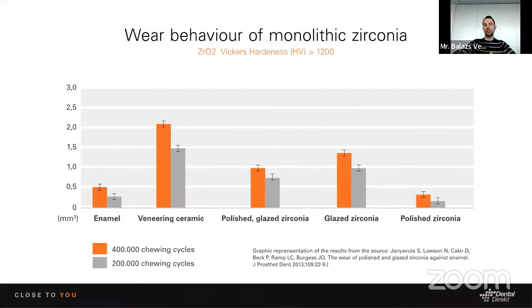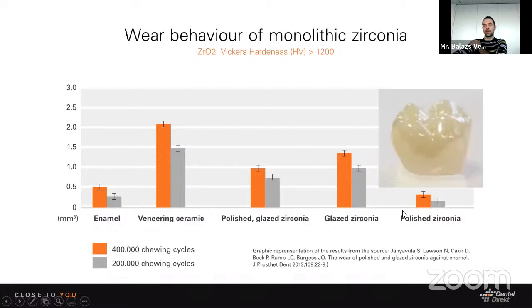We analyzed different kinds of materials. We saw that the enamel of the natural teeth has a certain hardness value, and we analyzed different kinds of materials regarding that, for example, veneered ceramics, polished and glazed zirconia surface, and glazed zirconia. At the end, we saw that the best solution is basically the one where we just polish the surface, because in that way we can avoid that rough surface that we saw in the scanning electron microscope picture. And in that way, we are almost on the same level, or even lower than what the enamel layer of a natural tooth has. So the best option will be a polished zirconia crown.